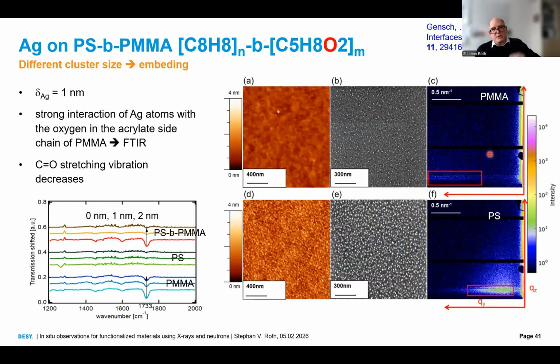We can change now to a slightly different system. We use silver on polystyrene-block-PMMA polymer. And just here, when we go through, keep in mind that PMMA, polymethyl methacrylate, has oxygen. And again, we do the same experiment. We spin coat a diblock copolymer film and the individual components. We make AFM, SEM, we make GISAXS, and already from only 1 nanometer of deposited silver, you see strong changes in the SEM, AFM, and also in the GISAXS.